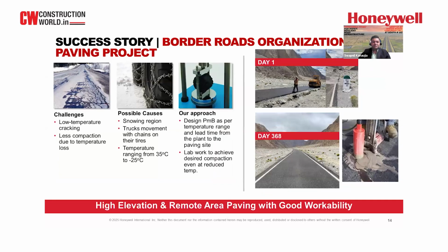So this case study was conducted in the northern region of India, in one of the highest altitude regions, approximately 17,000 feet, with temperatures ranging from around -25 degrees Celsius to 35 degrees Celsius. There we executed with BRO, the Border Roads Organisation. Being a mountainous region, the two major problems we understood were, first, low temperature cracking, and second, difficulty in paving due to the low temperature of the bituminous mix.